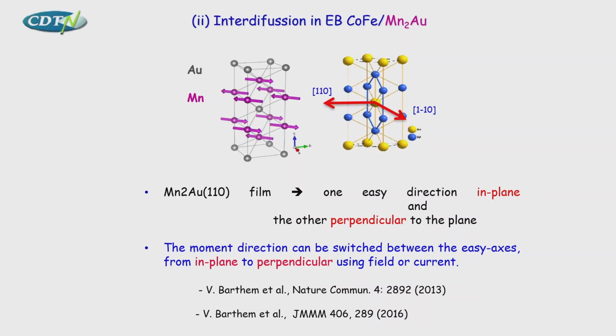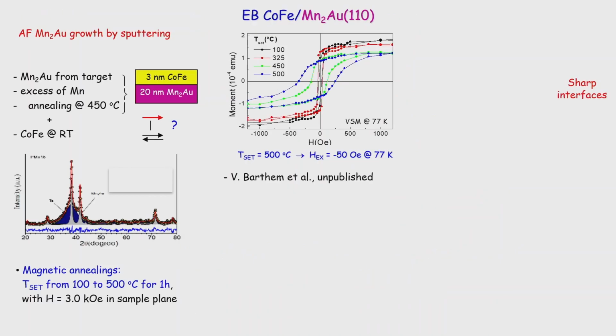different spin configurations that we see, small energy barrier. And then we started, in collaboration with Dominique Givord and Victoria Barthem, to grow manganese gold thin films. And then we succeeded to grow this kind of films by sputtering. And the only way to try to see if you have really antiferromagnetic manganese gold was to put a ferromagnetic layer and see if you get exchange bias, okay?